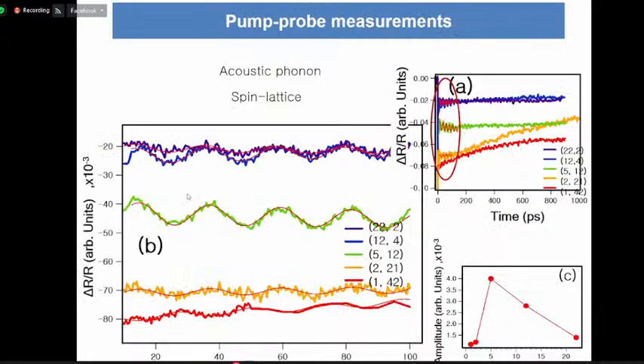This is a pump-probe reflectivity measurement as a function of time. We hit a laser on the sample, then the oscillation shows up like this. We found the intensity of this oscillation looks like this. This one also has a critical thickness around 5 unit cells. The amplitude of this oscillation is big compared to the others. It's similar to the magnetic hysteresis.